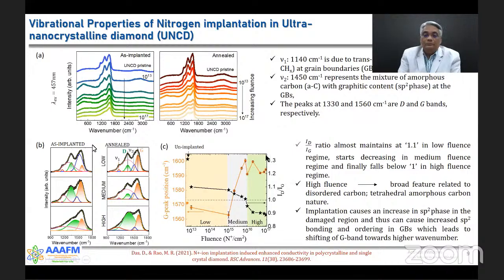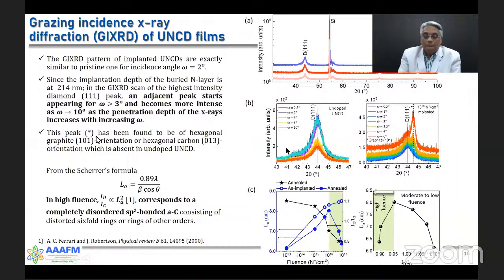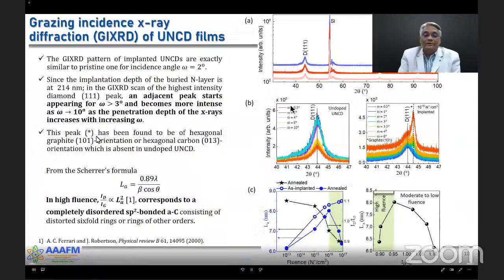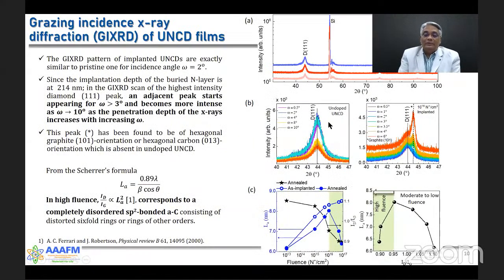Now, if you look at the grazing angle X-ray diffraction, this study has given us some interesting results compared to the undoped ultra nanocrystalline diamond. The implanted one shows an additional peak, 101. And then when the grazing incidence increases from 3 degrees to 10 degrees, by which process you're increasing the penetration depth of X-rays into the matrix, you'll see the intensity of this peak increasing, right? Which shows the effect of implantation clearly by the X-ray diffraction process.